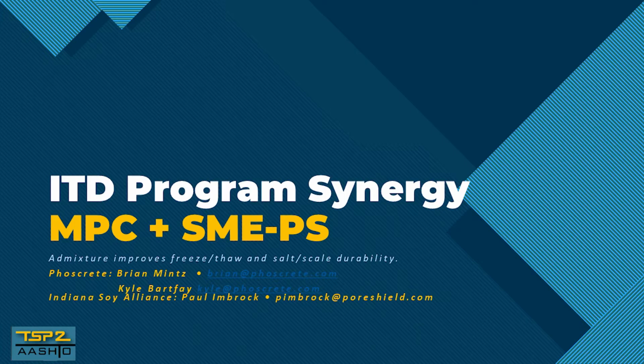One of the cool things that came out of the ITD program, especially with Phoscrete, is the sharing of knowledge. So when Pore Shield presented its durability capability using the soy methyl ester, or SMEPS, Phoscrete was searching for ways to better protect our installations from aggressive salts and freeze thaw. We tested Pore Shield as an admixture to Phoscrete, and we were surprised to learn that adding the soybean oil component did not impact any bond or compressive strength. It didn't mess up any of our ASTM tests, but it significantly helped our freeze thaw and salt scaling durability, and it reduced our already low dry shrinkage.